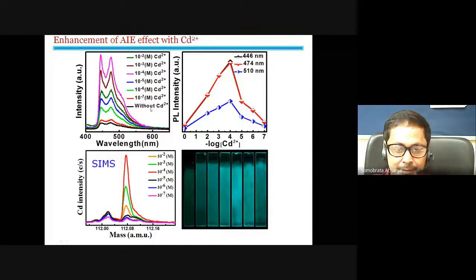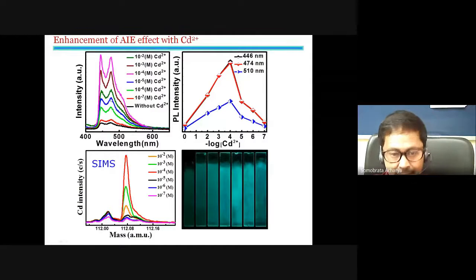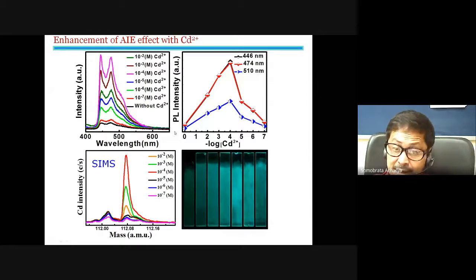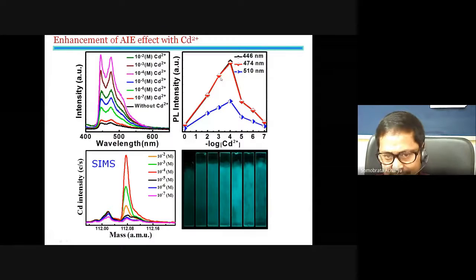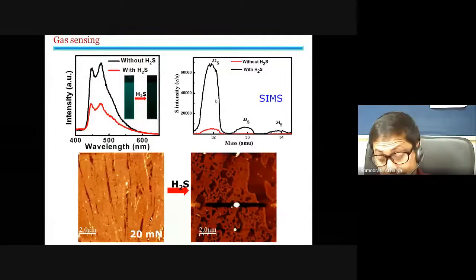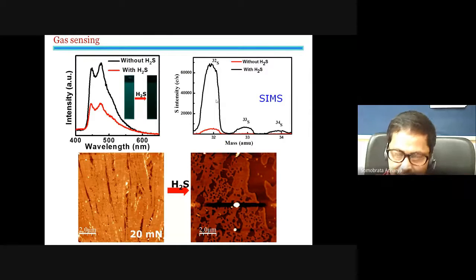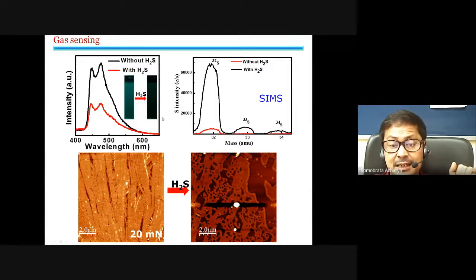so this gives you the example that without cadmium you have the luminescence like this. Once you add the cadmium into the surface, the luminescence goes up to a certain concentration, and after that it goes down again. So it can be used as the luminescence sensor, which can sense the doses of cadmium present in some system. Fine. One can also use it for gas sensing. For example, if you have the cadmium containing Langmuir film of these AIEgens, then you pass H2S there, and eventually you can see that there is a change in the luminescence there. So this change can be monitored, and this can be used as a gas sensor.